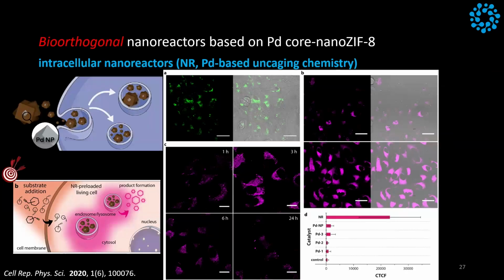So actually it worked very well with the two reactions, and this is the concept where you have a cell where you insert the palladium nanoreactors, that is a nanocube with a MOF on top of it. You have it inside a living cell, and then you start adding the substrates and see if you can produce the fluorescent product inside the cells. This is what we did. We produce the green product, and we produce also the pink product. These are the two kinds of reactions that we do. It works very well, and the more time that you leave the substrates, the more fluorescence that you get.